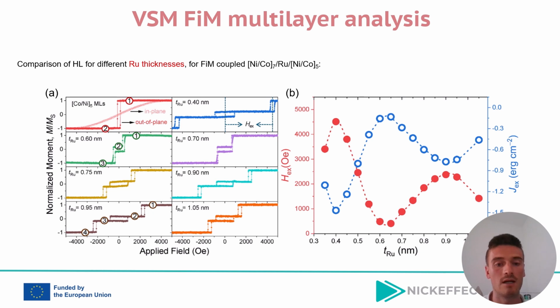Panel A shows out-of-plane hysteresis loops for different ruthenium thicknesses, revealing distinct switching fields and multi-step magnetization processes, indicating varying interlayer exchange coupling. The strong antiferromagnetic interlayer coupling is observed at specific ruthenium thicknesses, particularly at the local minima, which corresponds to around 0.6 nanometers.